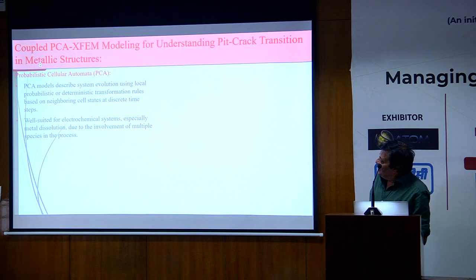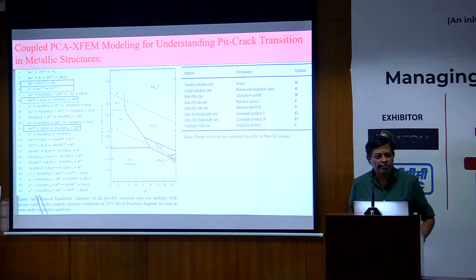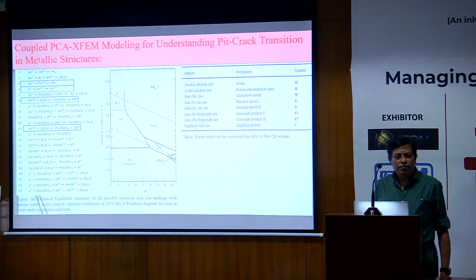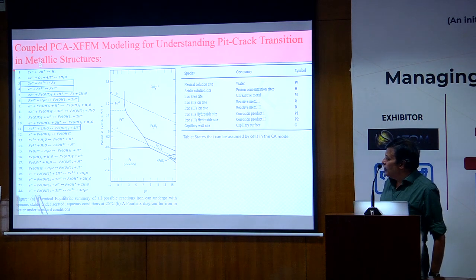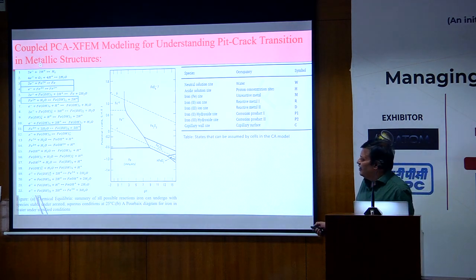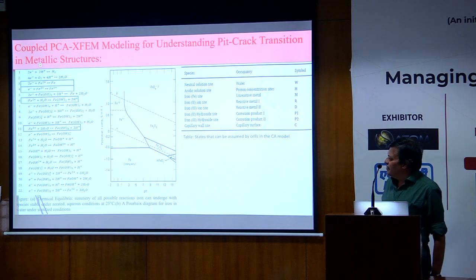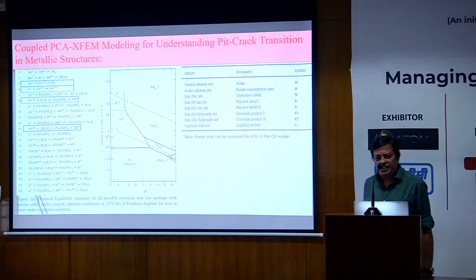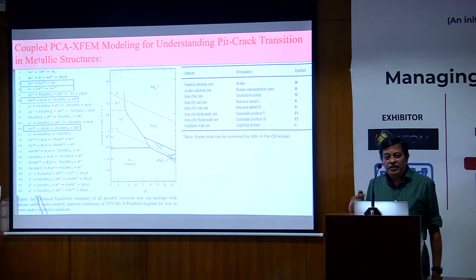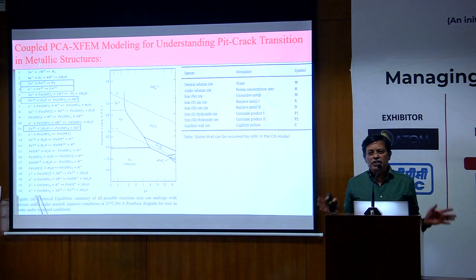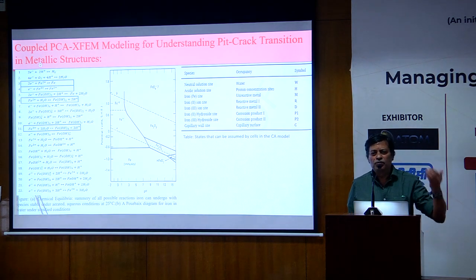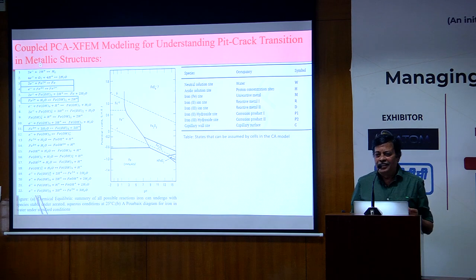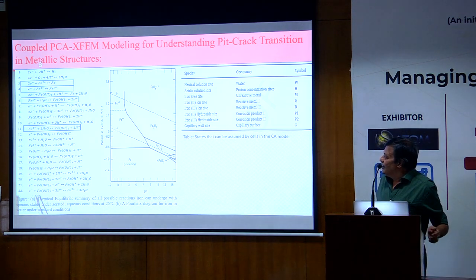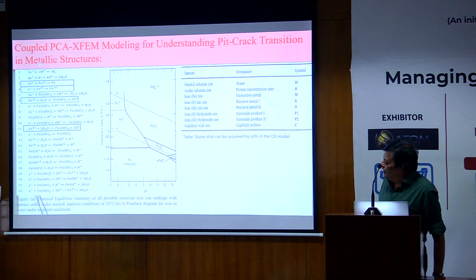So essentially, I am not going to talk much about pitting. One of the things needed for pitting is to find out what are the chemical species that form. So what we call the Pourbaix diagram is very important. This is well known for steel, but it is not well known for many other metals. There is an established procedure that we can follow. For example, if you try to do the same for the nickel-based superalloy, especially for hot corrosion, this is very uncertain. But for steel, there are 22 species, and 4 of them are very important.